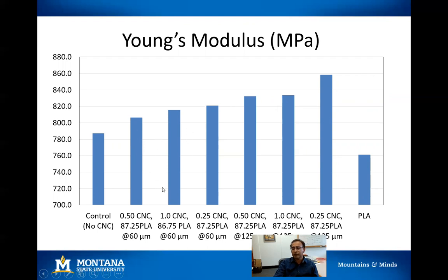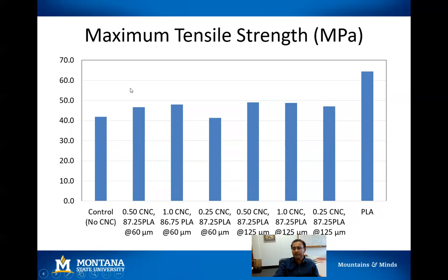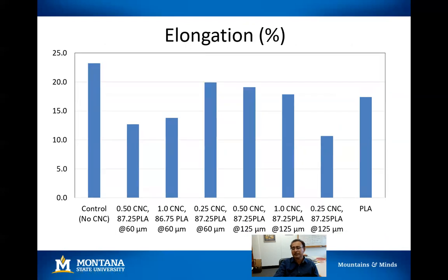And one thing interesting to note is that the composites with the bigger particle size DDGS showed higher improvement in the modulus than the lower particle size. The next property we looked at was the tensile strength of the composites. In tensile strength, we did not see any big increase with the addition of cellulose crystals. On the contrary, the tensile strength of the samples came down close to 25% when we added plasticizer and DDGS as well as cellulose crystals into the composites.